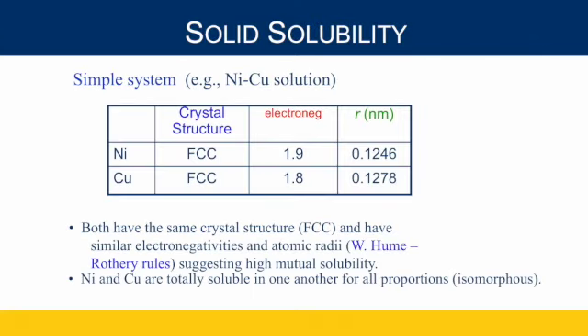Okay, so let's look at the most simple phase diagram that we'll see for metals, and that's nickel and copper. The reason it's simple is because copper and nickel are completely soluble with each other. This is very rare, actually. Most alloys, there's only a small amount of one solute that we can add to the solvent and still get a single phase. But with copper and nickel, they're miscible over the entire range from 0 to 100%. 100% nickel, 100% copper, 50%, anywhere in between, they're miscible. And this is because of the Hume-Rothery rules that we went over a few weeks ago. Their crystal structures are the same, their electronegativities are very similar, and the sizes of the atoms are very similar. So they can swap out with each other very easily.